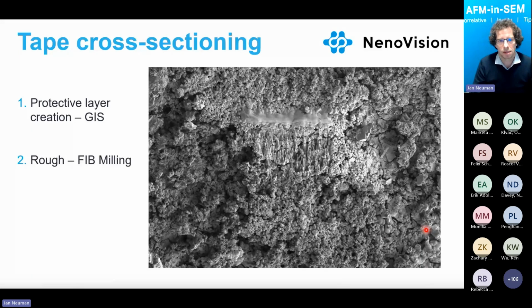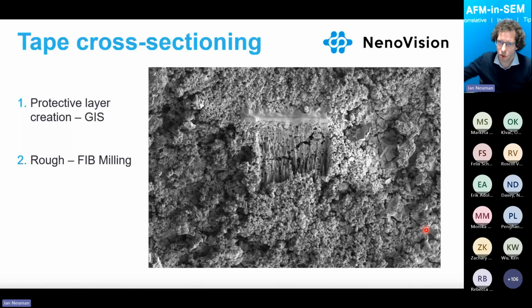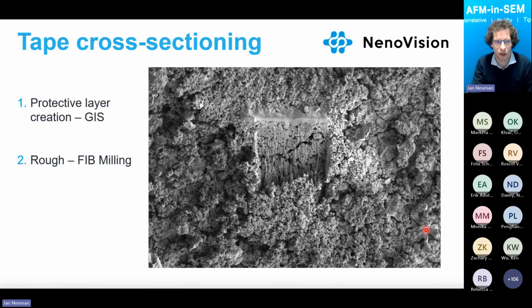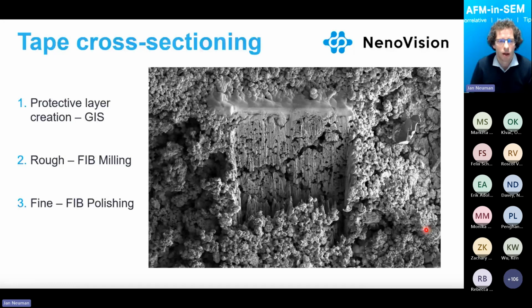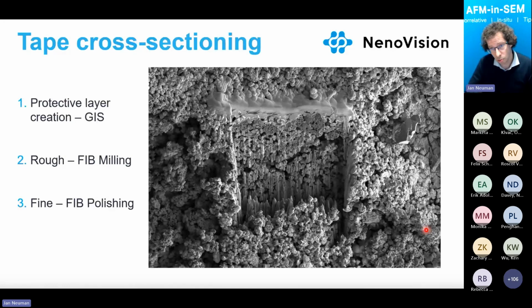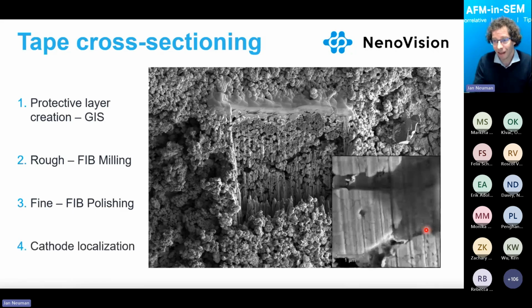Then the next step is a rough milling. So we are preparing the cross section, which we follow with the focus ion beam polishing to prepare a better surface. In this case, it's not optimal, it's just the visualization. And then, of course, you can use the SEM to exactly pick which cathodes you would like to analyze. Then you can come with the AFM and start the measurements.